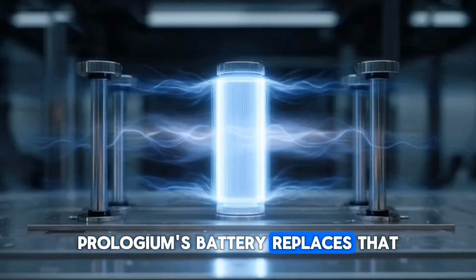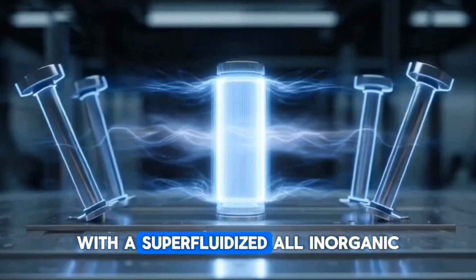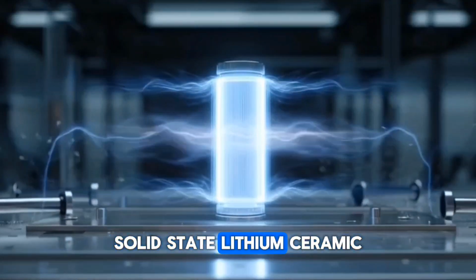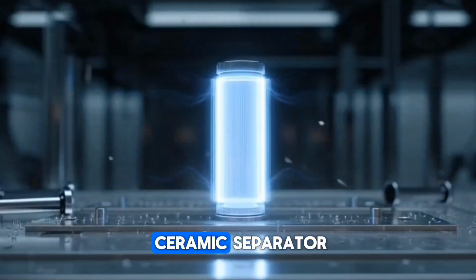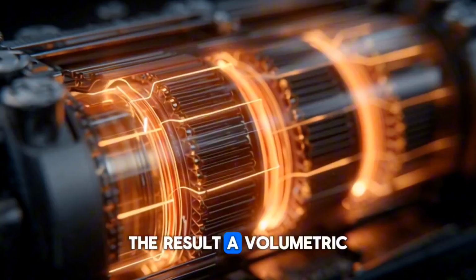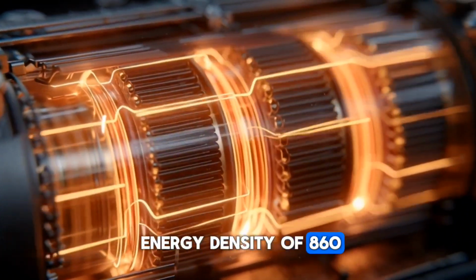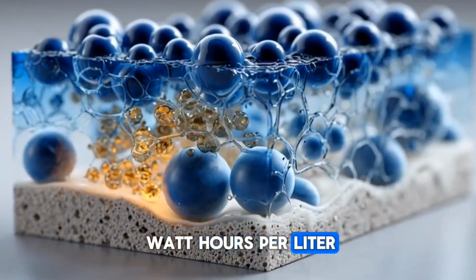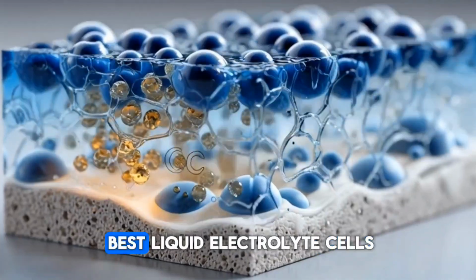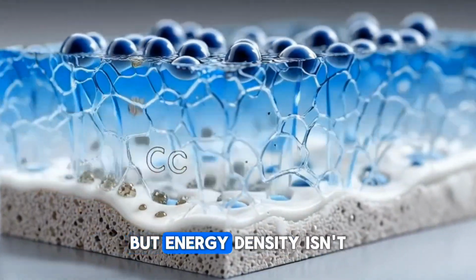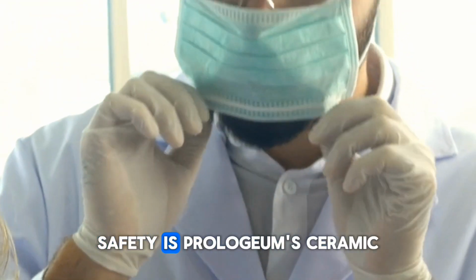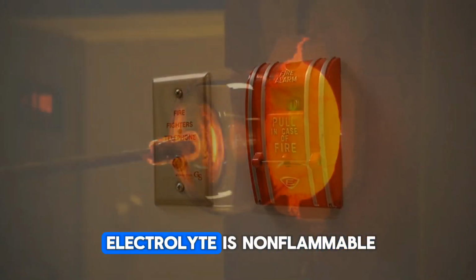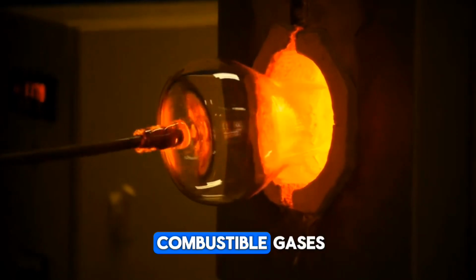Prologium's battery replaces that flammable liquid with a superfluidized, all-inorganic solid-state lithium ceramic electrolyte and an all-ceramic separator. The result? A volumetric energy density of 860 watt-hours per liter, significantly higher than today's best liquid electrolyte cells. But energy density isn't the headline, safety is. Prologium's ceramic electrolyte is non-flammable and does not release combustible gases.